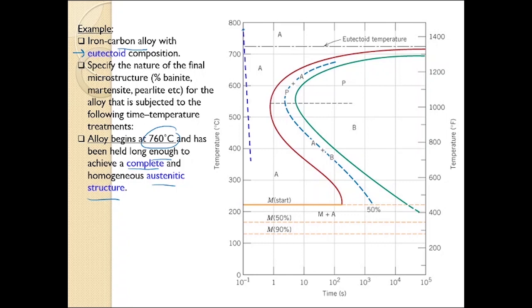Okay, so we start around over here, and then to get bainite, we need to supercool it until around 300 to 400 degrees Celsius, and then we maintain at that temperature for 10,000 seconds. 10,000 seconds is over here. So we get bainite microstructure, and then we cool it down. If we stop over here, we will get 50% austenite, 50% bainite, because if we continue to maintain at this temperature, it will transform until 100% bainite, as you can see.